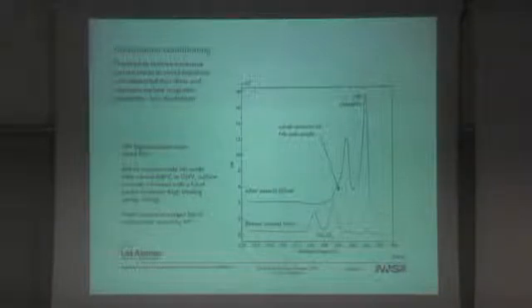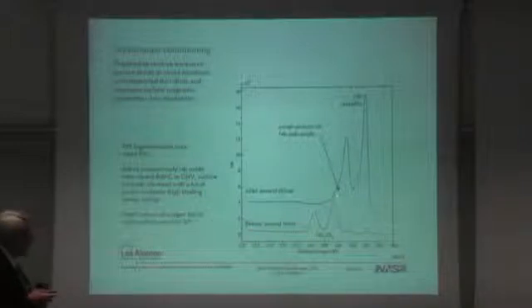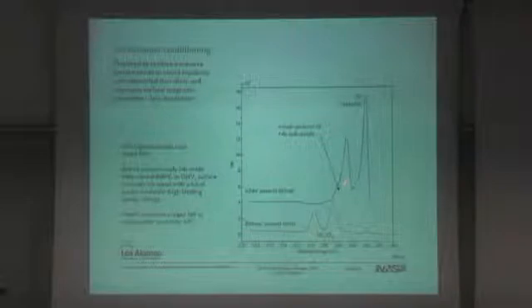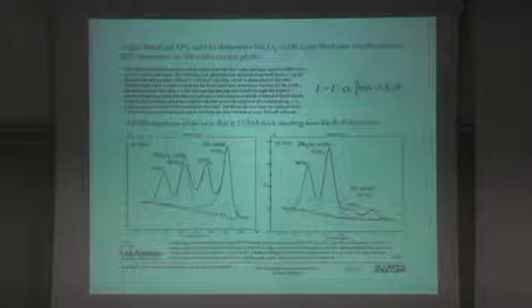Now if we anneal that up to 800 C, this particular one was done 800 C for four hours in UHV. Obviously the Nb2O5 disappears. We're dissolving the oxygen into the subsurface. And the metallic niobium peaks show up. However, it's not perfect. If you look, there's still some oxygen left, and it's substoichiometric oxygen now. It's not Nb2O5. And that's actually shown here as the tailing, the substoichiometric niobium oxide is shown as the tailing to higher binding energy. So you might actually consider that as being a defected oxide. That's a good way to view it. And these might be actually magnetic pinning sites that we should possibly be concerned with.